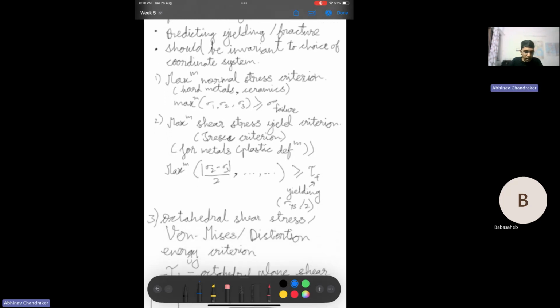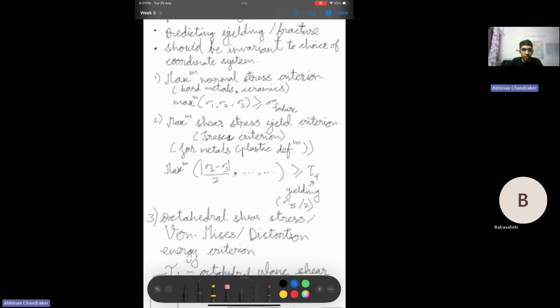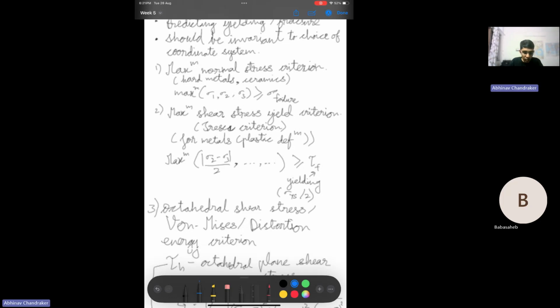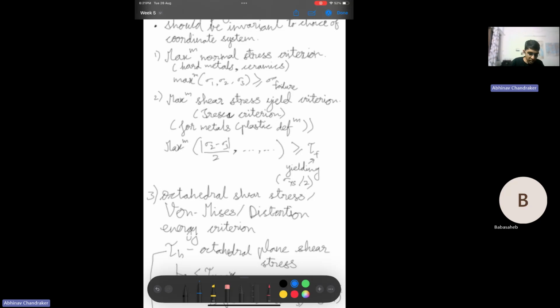So considering this philosophy, there were multiple criteria which came up in the last century. One criterion is the maximum normal stress criterion. I'll go a bit quicker since this is covered in detail in the slides. Here we look at the principal stresses for the stress field, and what is the maximum value of the principal stress in any direction. If that is more than the stress required for failure, it could be for yielding or for fracture, then we say that the component will fail, and that is the threshold stress that can be applied.